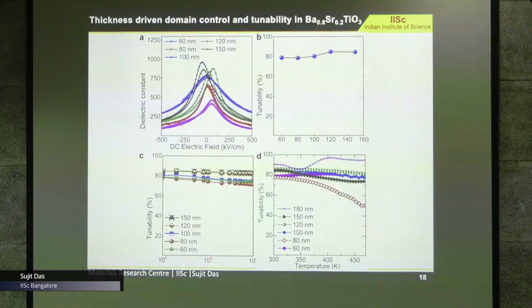We take this particular composition, BST20, and grow different thicknesses. We see that the dielectric constant is enhanced with the thickness, and tunability is also enhanced with the thickness. The frequency stability is also pretty good for all thicknesses, and the temperature stability is also pretty good for all thicknesses except the 80 nanometer one.